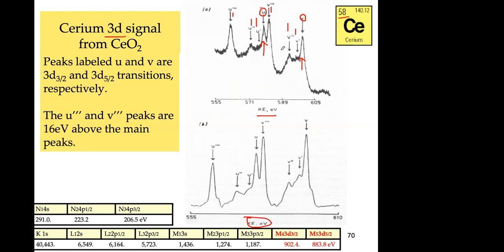The beauty of this spectra is that this is a quantized transition. So you can, in principle, see the difference in energy between the different levels, because the difference between this peak and this peak is a difference between two electronic levels of cerium. And if you look at the difference in energy between these two peaks, that's the difference between two levels. So to a certain point, you can have some information on the electronic levels of cerium, external levels obviously, where the shake-up transition occurs. So that's sort of impressive.